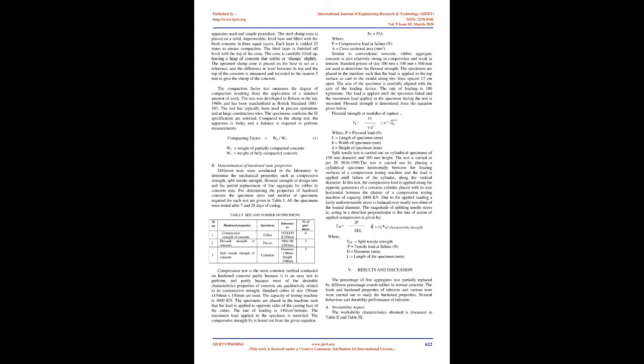On the basis of his analysis he concluded that the higher the rubber content in the mix, the higher the reduction in compressive, tensile and flexural strengths. Hence it is not recommended to use this modified concrete in structural elements where higher strength is required, but it can be used in many other construction elements like partition walls, road barriers, pavements, sidewalks, etc. F. Hernandez Olivares et al., 2002.